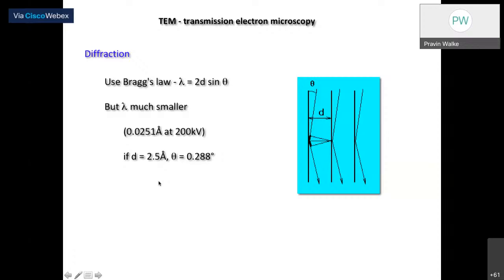What is important here in the diffraction pattern, as I just said, is that the diffraction pattern shows differences for different samples, right? So what makes the difference? As we know Bragg's law, where lambda plays a very important role, right? And your lambda is much smaller in the case of TEM, because we are using a very high potential difference. So we can easily reduce the lambda value here, right? And then we can find the resolution is up to 2.5 angstroms, if your incident angle is 0.288 degrees, a very small incident angle here.